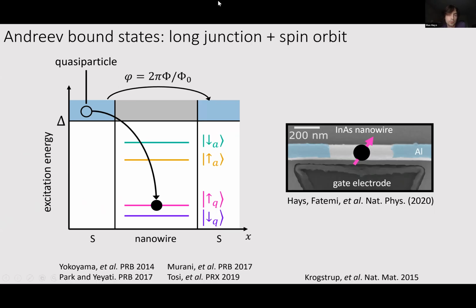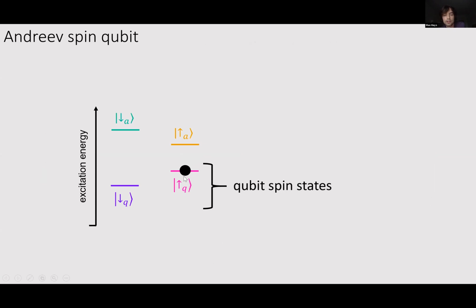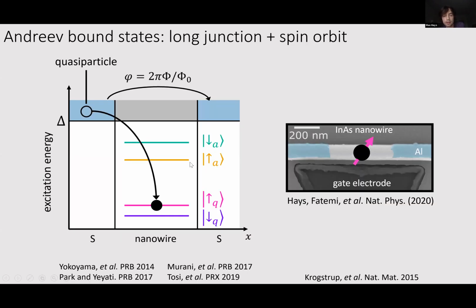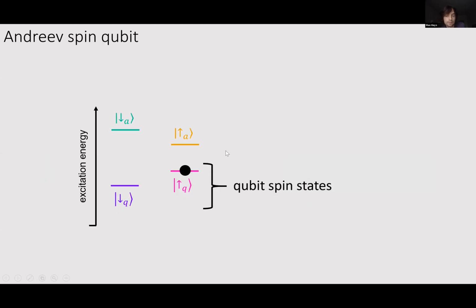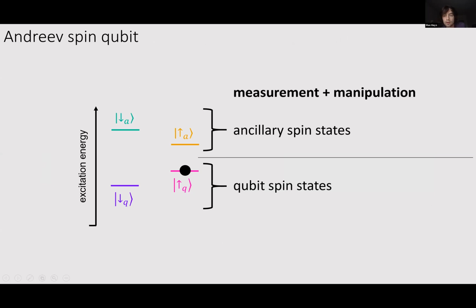So instead, we take advantage of the long junction and spin-orbit effects. This does a couple things. It brings us to this regime where we can have multiple doublets. And thanks to spin-orbit effects, in combination with the flux, this actually breaks the spin degeneracy, and so we can have two doublets. We still have this lower doublet, these two spin states, which we label spin up, spin down sub Q for qubit. These are going to form our qubit states. And then we also have this upper doublet, spin up, spin down sub A for ancillary. These states, while they don't form the qubit, are going to be critical both for readout and manipulation of our qubit. So we have our qubit states and our ancillary spin states.